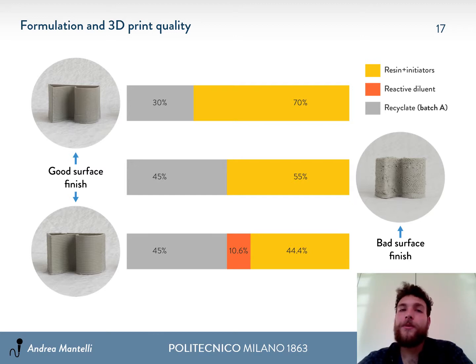Even though we have a printable material, we saw that some formulations produce a bad surface finish in the 3D printed object. For example, here you can see that the formulation with 45% of recyclate on the right turns out badly from the 3D printing process. By adding the reactive diluent to the resin, we can produce an object with a better finish, even though we still have a high content of recyclate.